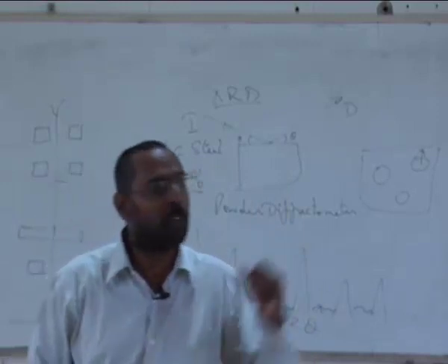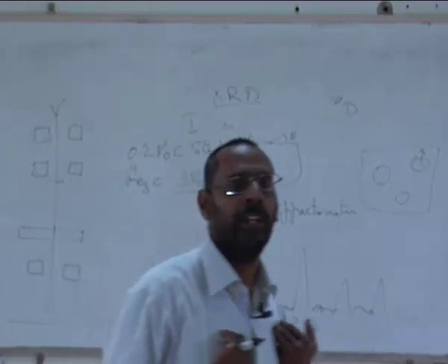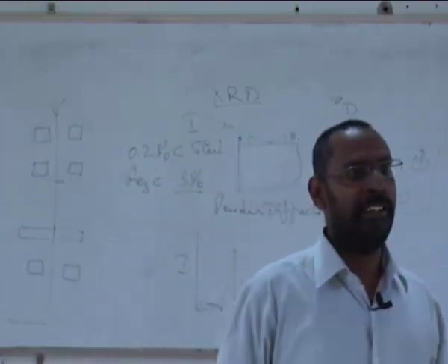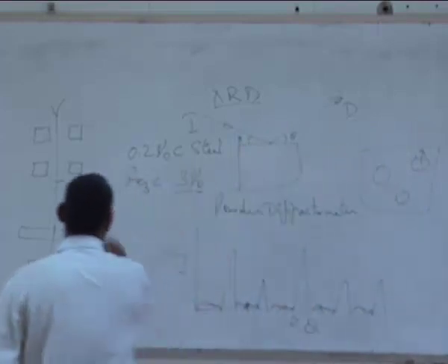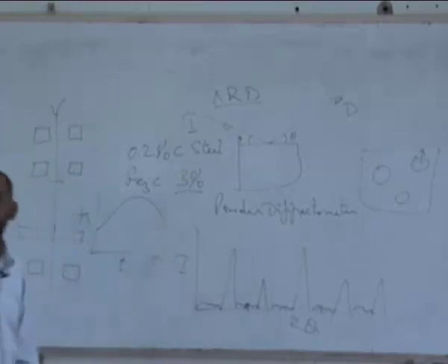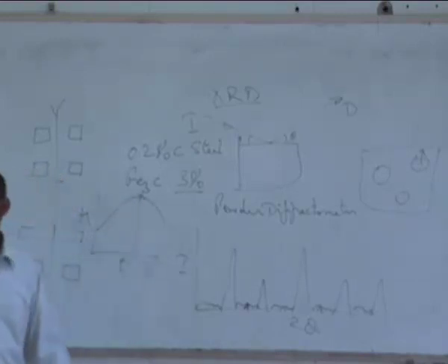Whether these precipitates are coherent precipitates, or semi-coherent, or incoherent, why am I bothered about it? I am bothered about it because the properties of my alloy depend on that. If I do age hardening and plot the hardness versus time, you see that this is the type of curve that I get, right? This curve tells you that I get a peak hardness somewhere here.